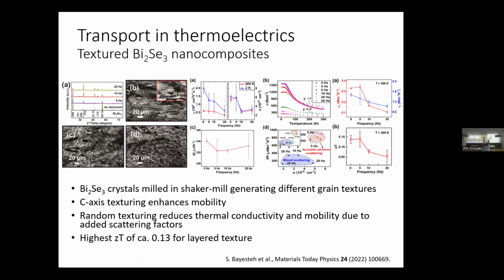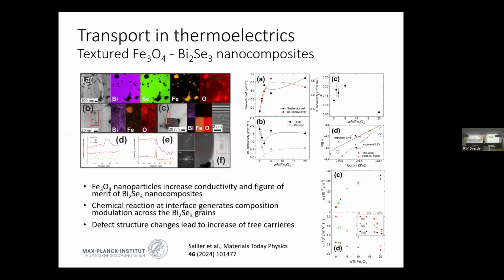If we have this type of structure, our working hypothesis at the moment is that we have two things happening at the same time. We have, of course, bulk carriers, so normal band conduction, that dominates. In that situation, because we have a strong impediment to bulk conduction, another part that also exists in this particular material, which would be surface states, which have plenty of surfaces, somehow starts to show. Surprising for us is to evidence that it is not a surface to the vacuum, as is normally predicted, but a surface to itself. So we think, and we can show it later, that the touching points in this type of materials are kind of vacuum enough to start showing. In the case of the samples with the iron oxide, there is more to it, because the localization phenomenon changes with the amount of iron oxide that we put in there.